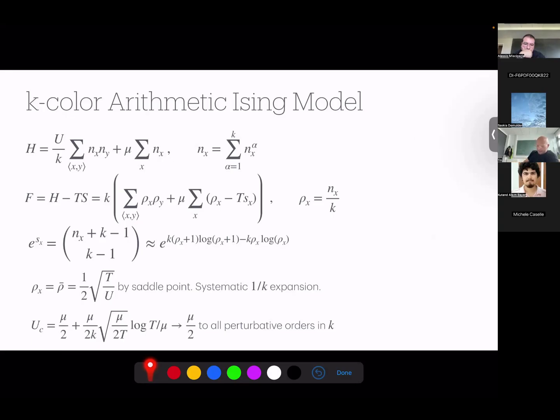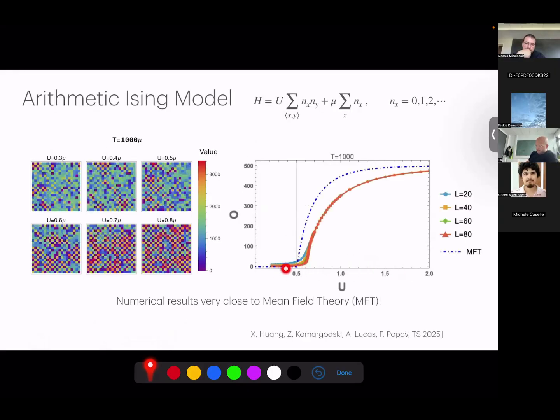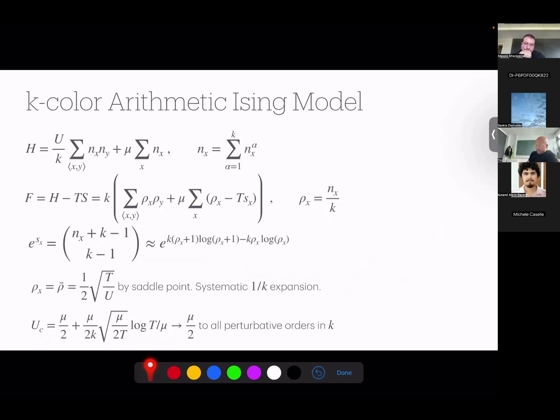And moreover, this critical U at very large temperature, as you can see here, there was some critical U, which was very close to 1/2. This is in units of mu, if you remember. It turns out to have a correction, which is a 1/k correction, but which also vanishes as T goes to infinity. It is a log T over square root of T correction. And it seems that this is true to all perturbative orders in k. We have some arguments that this may be true to all perturbative orders in k.